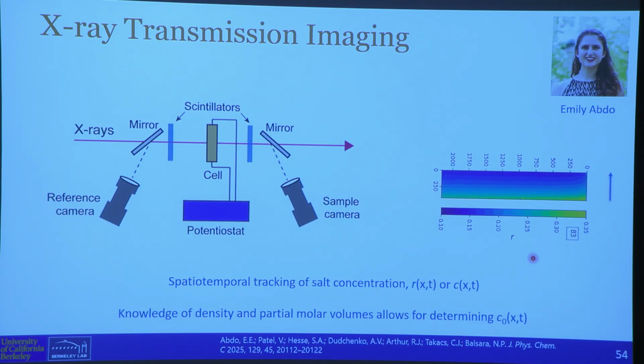Okay, you can see initially, and it goes back and forth. It's sort of uniform at some time. It's now uniform, and now the gradients are developing from the top and the bottom, and eventually saturating. Okay? So you're seeing that as real time goes by, this is experimental data, of how these gradients are developing. In the top of this electrode, the lithium ions are coming, and the concentration is going up from average. In the bottom, the concentration is going down from the average, and we have this in situ data at ridiculous